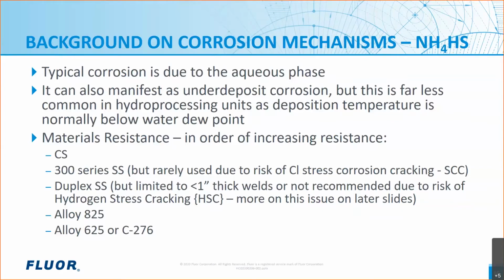It can also manifest as under-deposit corrosion, but this is far less common in the hydroprocessing units, as the ammonium bisulfide deposition temperature is normally below the water dew point. So there's already water present, even if you're upstream of there. So if deposits were to possibly form, they are often washed away. But the number one way we avoid ammonium bisulfide corrosion, if it is predicted to occur on carbon steels, is by upgrading materials.